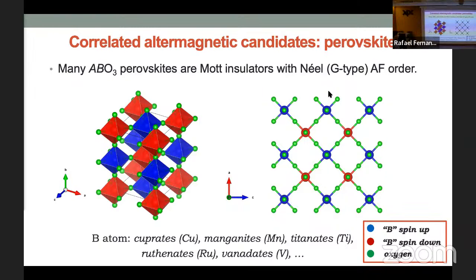So this is just a picture of an ideal perovskite structure where you have the oxygen octahedra, and inside you're going to have either copper, manganese, titanium, ruthenium, or vanadium. And these have been studied for lots of different reasons. They have in common that all of them, in some regime, are Mott insulators. Okay, and here's just a projection of the plane showing this octahedron. Okay, all right. So this is a Néel type antiferromagnet, also called G type order.